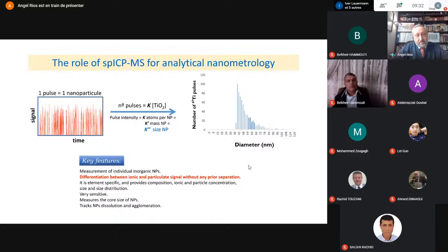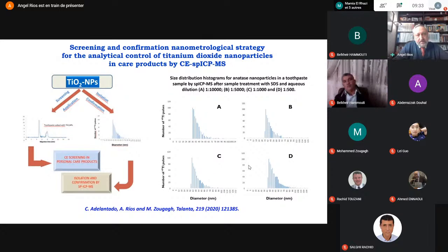In fact, this technique offers interesting features because it allows differentiating between ionic and particulate signal without any prior separation, is very sensitive, very selective, and it provides very interesting information about the amount of nanoparticles in the sample, and also the size distribution of these nanoparticles. We have developed in this line a nanometrological strategy for the screening and confirmation of titanium dioxide nanoparticles, now in this case in personal care products, by using just this technique that you can see in this slide.